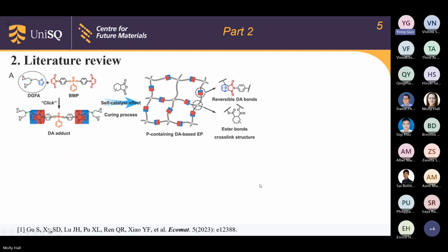The authors used the bio-based monomer DGFA to combine with the phosphorus flame retardant structure to achieve a phosphorus-containing DA-based epoxy resin and applied it on the CFRPs. And the bio-based carbon content of this DA-based epoxy resin is 28.6%.